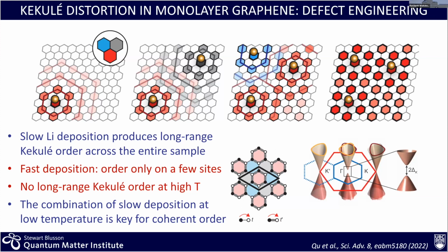So in this dilute lithium case, is the doping effect of the lithium atoms ignored? But what about the silicon carbide? Does it also dope the graphene? In the dilute case, we don't see doping of lithium into the graphene. And you're asking what happens below? The silicon carbide is still doped, but not by lithium. Basically, the silicon carbide doesn't contribute anything as far as the electronic structure and the chemical potential. All you see there is graphene itself. Is there a way to get rid of the doped silicon carbide itself?